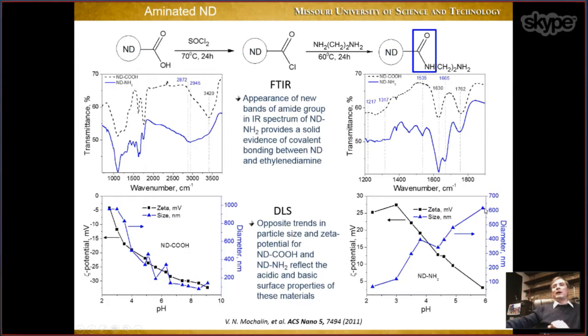Aminated material becomes better dispersed at acidic pH, sorry. And again, it's in agreement with its basic character because amino groups get protonated when we shift pH to the acidic range, and now we have NH3+ on the surface, so all diamonds have positive charge and they again repel each other and stay well dispersed. Fine, so what can we do with this material, with aminated nanodiamond?